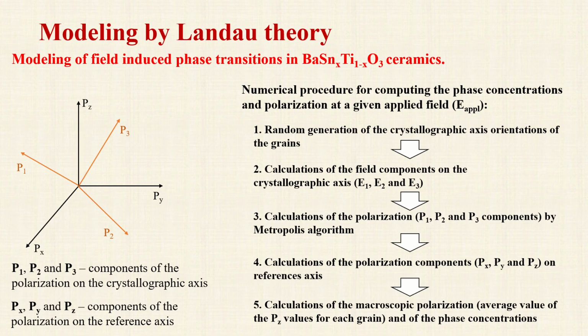Therefore, we improve the previously described algorithm with the following steps. For each grain, random orientations of the crystallographic axis are generated. The components of the electric field on the crystallographic axis are then computed and introduced in the Monte Carlo algorithm to obtain the components of the polarization on the crystallographic axis.